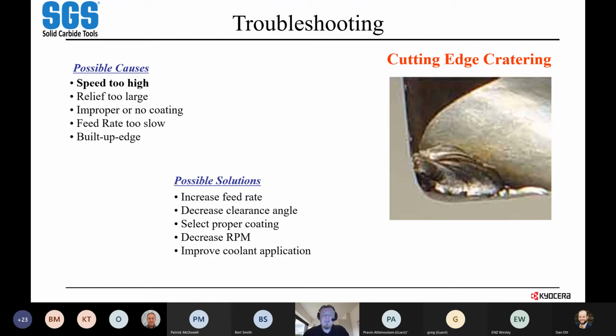Feed rate being too slow is usually a good culprit here. That material flowing across that rake face and into the flute is not pulling enough heat away from the material itself. It's not a large enough chip to break away and pull that heat out, so it builds up, and that pressure of that chip running across there slowly starts to wear a divot basically into that rake face. And eventually it's just going to cause it to wallow out, and it's going to crack out on that edge because there's just not enough material there to support it as well.